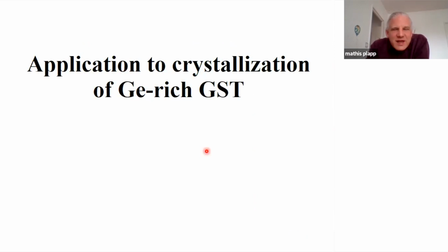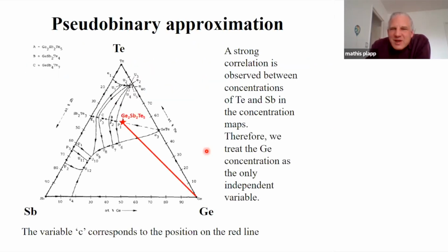Okay, so let's see how I can apply all this to the crystallization of GST. Well, we need to do a lot of approximations. The first thing is, instead of doing the full ternary system, we do a pseudobinary approximation. So we have our system living on this red segment in the general ternary GST. We have a single concentration variable that is on that segment between the stoichiometric GST phase and pure germanium. This is justified by the fact that in all the concentration maps, antimony and tellurium are always strongly correlated.